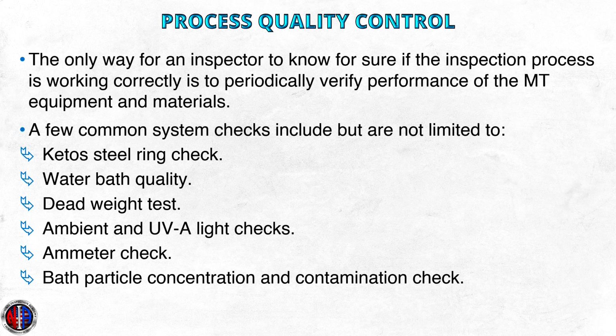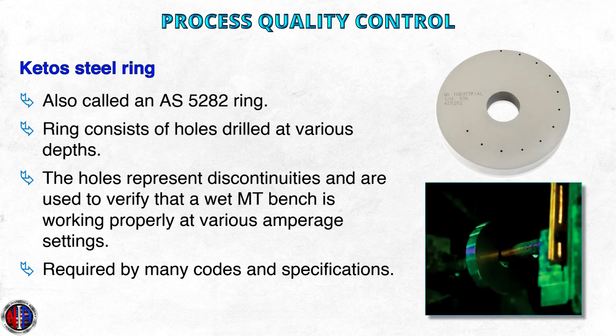The Ketos steel ring. One of the more commonly known discontinuity standards for magnetic particle testing is a Ketos ring, also known as an AS5282 ring. Each type of ring has holes drilled through it at various thickness depths, with the first hole drilled close to the outside surface and the last hole furthest away. These drilled holes represent discontinuities and are used to verify that a wet MT bench is working properly at various amperage settings and is required by many codes and specifications to validate MT performance.